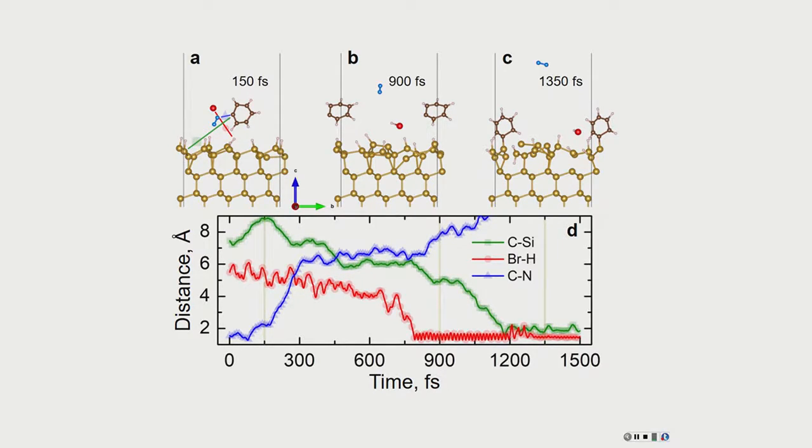Okay. So this is bulk silicon, right? Silicon 111. Yeah, I know that it is around 800 to 1000 degrees Celsius for silicon 111 to reconstruct, and the structure is completely different. I'm not sure that is applicable here. If that is applicable, then what would be the position of that functional group? Like on which atom, or somewhere else?